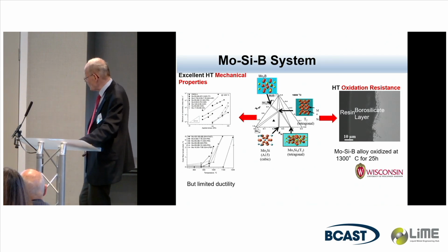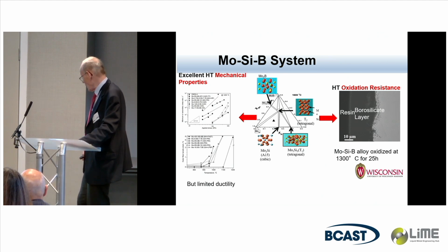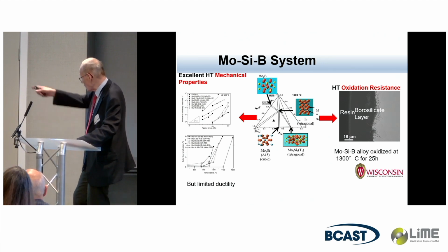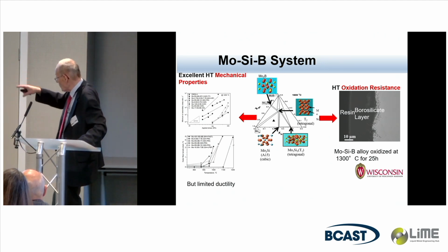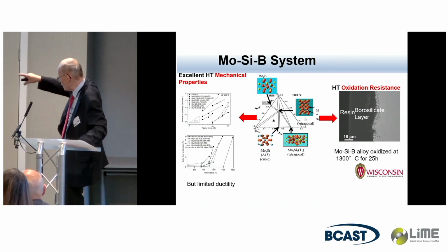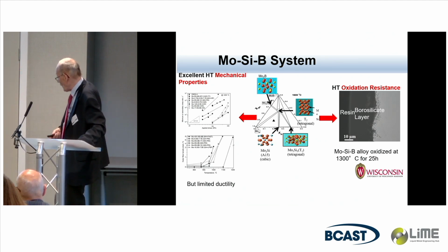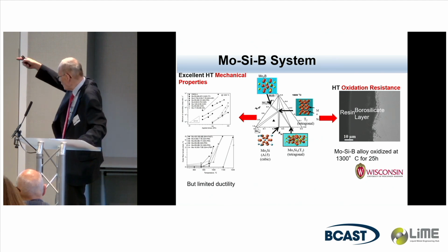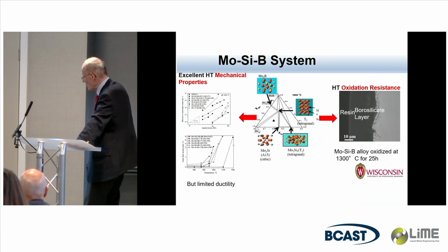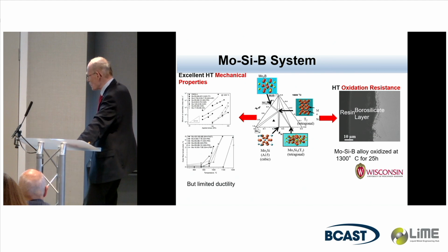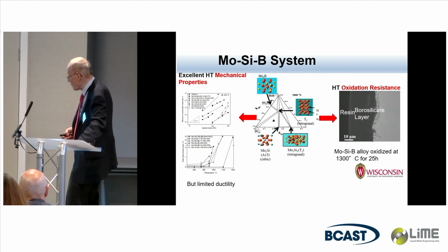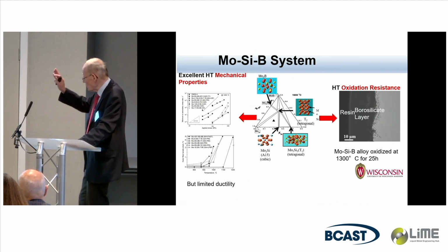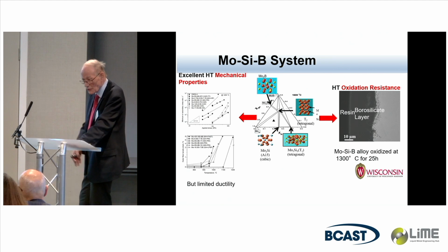So one of the systems we've been looking at as part of a RAPID program is the moly-silicon-boron system. Here there's a tie-triangle between a molybdenum solid solution and Mo3Si phase, and a ternary intermetallic Mo5SiB2. This phase is very densely packed and has a very high melting point. So the liquidus temperature is above 2100 degrees Celsius.